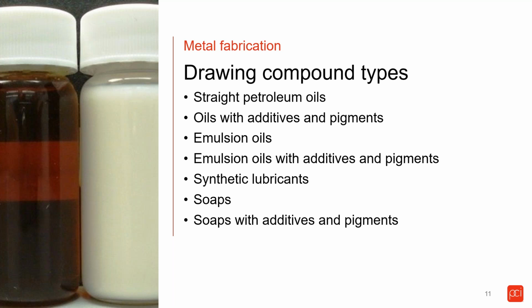Synthetic lubricants are becoming more popular due to them being a lot more environmentally friendly than straight petroleum oils. The synthetic lubricants, though, since they don't have any petroleum in them, have to have extra corrosion inhibitors built into them to make them as robust as a straight petroleum oil. And then soaps, like I mentioned before, the stearates are soaps. They generally are a dry film versus the rest of these listed here, which are liquids. Like I said, they will cause a lot of issues with foaming in your stage if you don't have the correct cleaner.